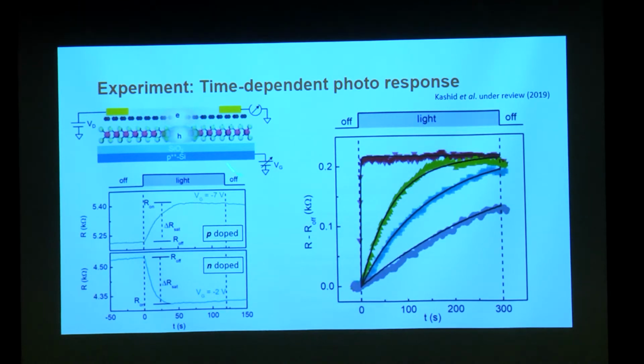We initially thought there was some dirt sitting in the middle, but those things were ruled out one by one. And more interestingly, when you increase the power incident on the molybdenum disulfide, as I increase the power here, the speed at which the current goes to the final state becomes enormously fast. It's a power-dependent relaxation rate, which is also a very surprising result. Why should the speed at which electricity is formed after light comes in depend on how many photons I am shining?